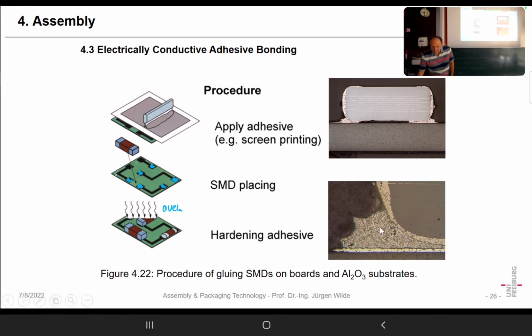Here we can see several things. One is the silver flakes. What appears dark is the epoxy. Also, these small noses are more or less a result of the screen printing process. So you could say probably the mesh distance is something like the distance between these noses here. So that process works very well.